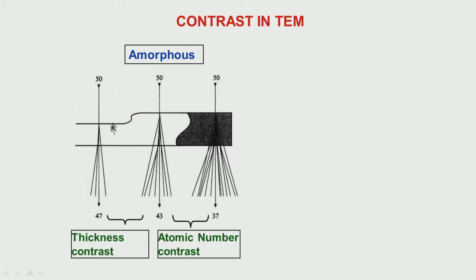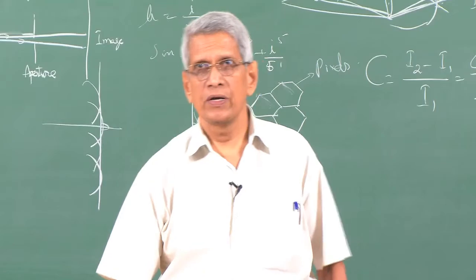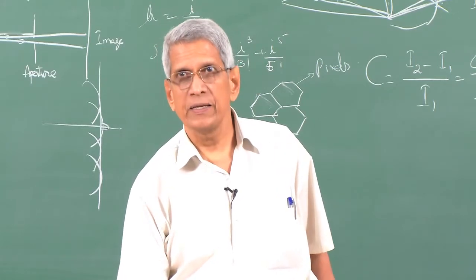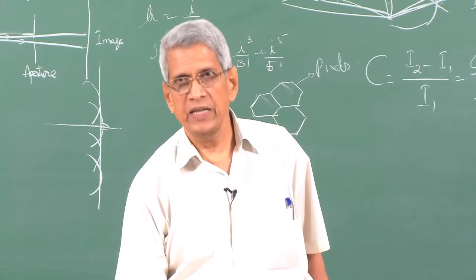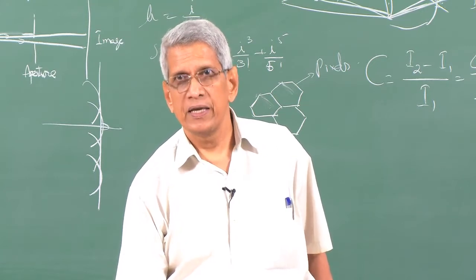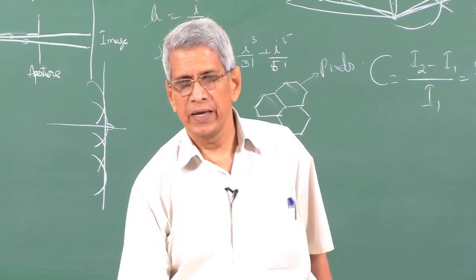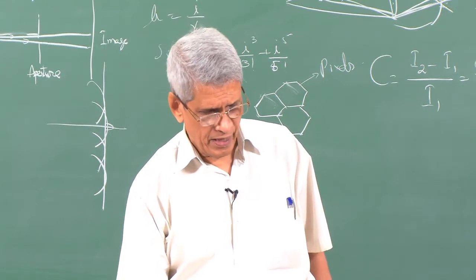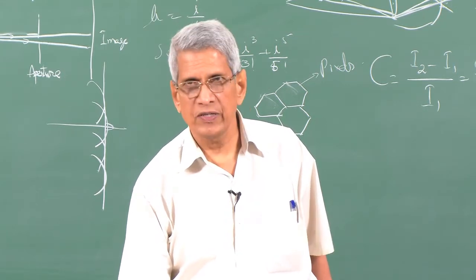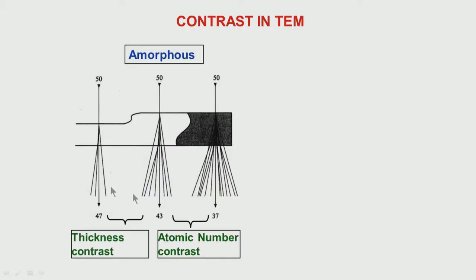But if the thickness of the sample increases, then the absorption will increase. So this will give rise to a reduction in intensity. That means that if there is a variation in thickness of the sample from one region to another, that will be reflected as a variation in intensity, and now we can see it as contrast in that sample.